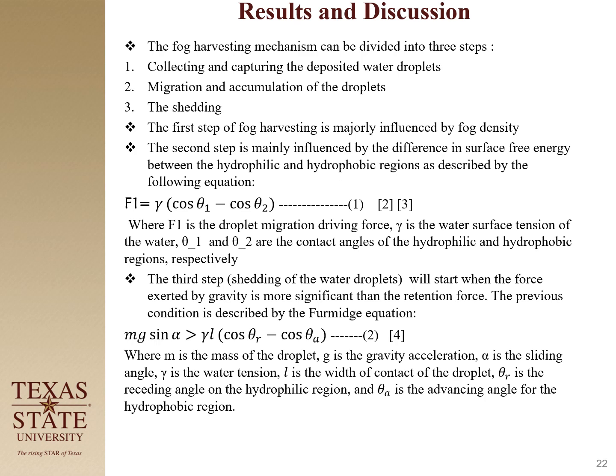Now, the mechanism and why this collection is happening in this particular way, where hybrids are achieving a higher water collection rate, can be explained with the 3 stages: first capturing the droplet, second migrating and accumulation of those droplets, and finally shedding.